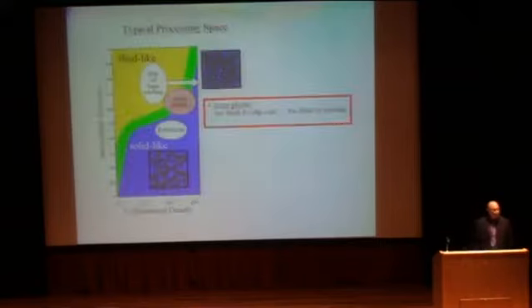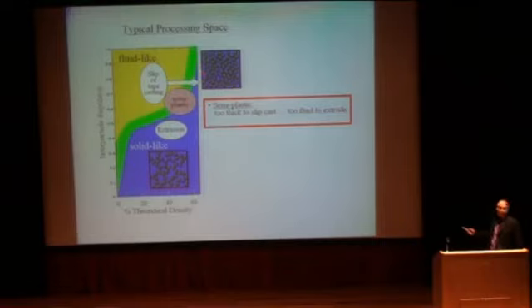So if you apply the same concept to particulate systems, colloidal particles in particular, you have a situation where you can describe ceramic processing. So we've got the interparticle force, how the little particles repel each other, versus how dense they are, versus how many particles you have within your water system or your solvent system. Now, when we do slip casting, we make sure that the particles are fairly repulsive, and that the density is fairly low in the slurry, say 30 volume percent solids.